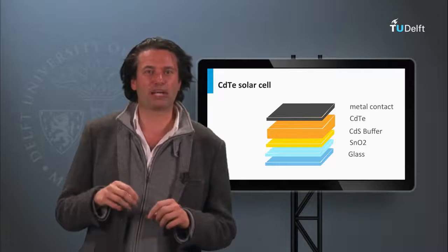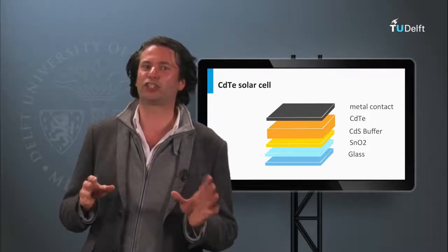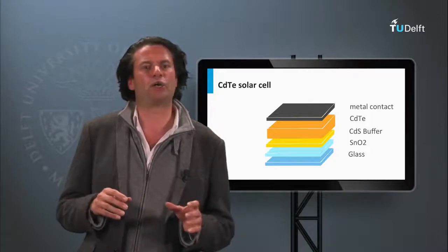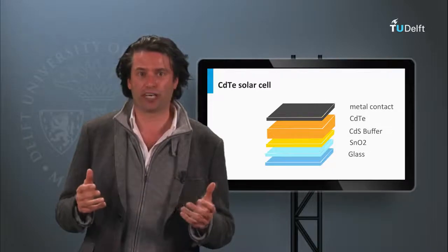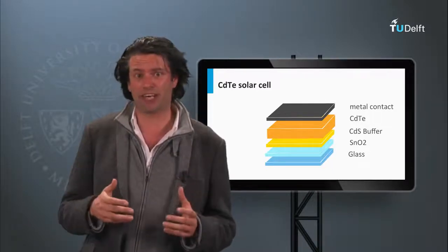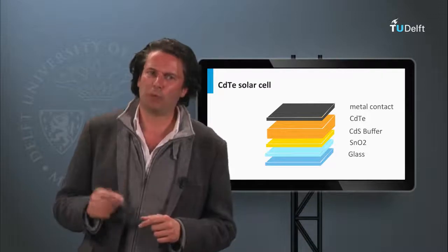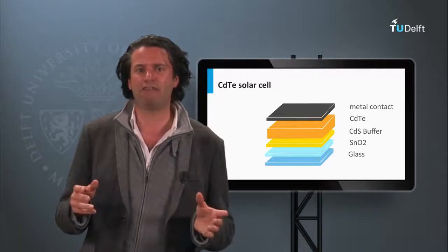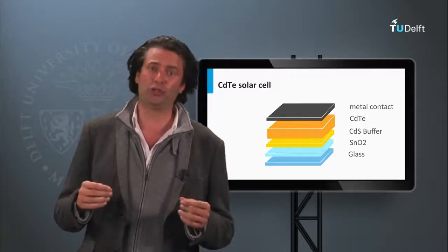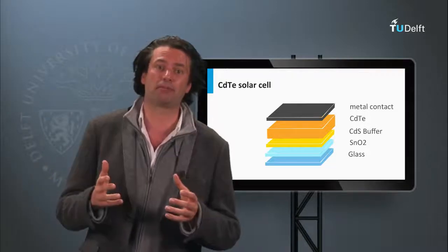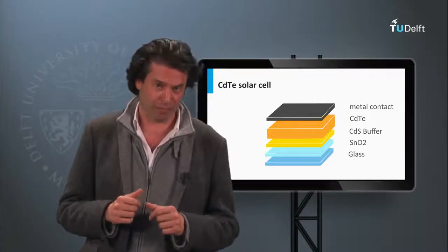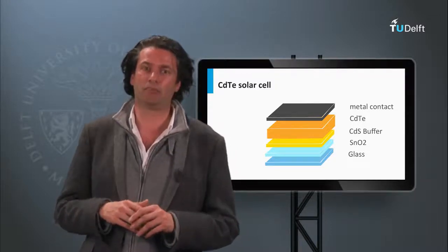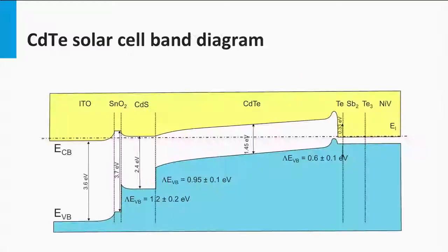The material properties of cadmium telluride do not allow a large choice of acceptable metals. Heavily doping the contact area with a semiconductor material improves the contact. However, achieving high doping levels in cadmium telluride is problematic. Copper-containing contacts have been used as back contacts. However, in long timescales they may face instability problems due to the diffusion of copper through the cadmium telluride layer up to the cadmium sulfide buffer layer. Nowadays, a stable antimony telluride layer in combination with molybdenum is used.